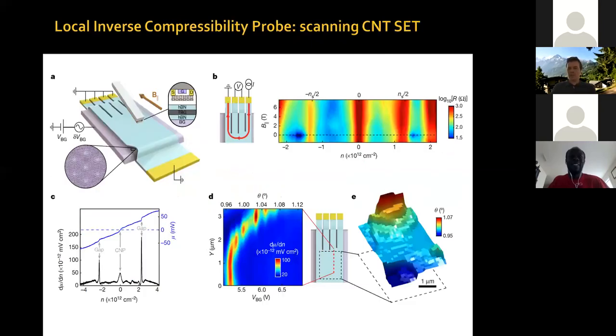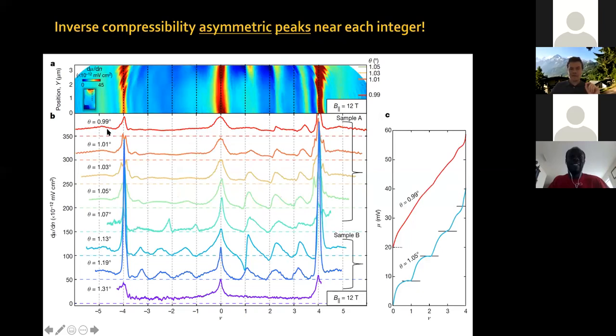So remember, we're doing our compressibility measurements locally. So I can sit in a given spot in my sample and measure dμ/dn versus density for that particular region, okay? So all of these compressibility curves look different for different twist angles. And how am I going to a different twist angle? I'm just changing spatially to a different spot where the twist angle locally is different, okay? That I understand, but did you know in advance that the compressibility for a particular twist angle would look like this, and then based on the...